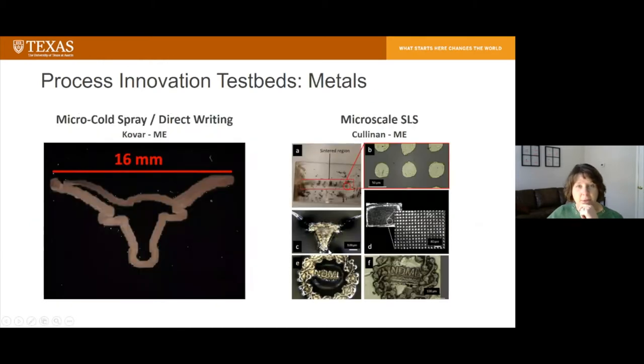Here's a couple of examples of metal test beds that are under development. On the left, we have micro cold spray. This is also from Professor Kovar in mechanical engineering. And in this particular case, this process is capable of depositing patterned thick films. It basically uses a high velocity impact of submicron particles onto a substrate. The neat thing is that the substrate can be polymer, metal, ceramic. I've even seen them write onto Kleenex.